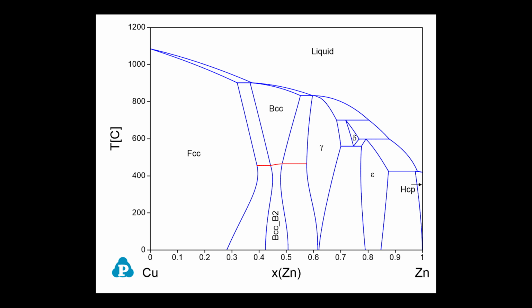I still really liked the idea of trying to find a way to create the brass without boiling off any zinc at all. In attempts to do this, I decided to try to ride the phase diagram. By making a mixture of copper and zinc that's biased with higher percent zinc than our target, we would be able to make a solution that liquefies copper below zinc's boiling point, since the alloy that it creates has a lower melting point than the boiling point of zinc. Then, since the liquid is not just liquid zinc, it's liquid brass, we can bring it above the boiling point of zinc and have significantly less zinc boil off than otherwise. And then I can increment the temperature and add more copper stepwise until we have our correct ratio with almost no boiling zinc at all.